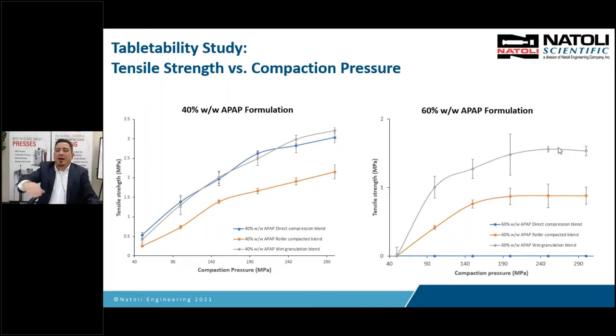This is what I'm talking about with pushing our product until it fails. You see, as we increase pressure, we have this linear portion. Now it's starting to level off. Now it's really leveling off here. Same thing with the dry granulation, a roller compacted blend. You've got this linear portion. Now it's leveling off. This leveling off here is where we reach this maximum compactability or compressibility. We really don't want to compress in that area, because when we're over compressing in this area, this is where we see capping. Capping issues occur when you reach this maximum compactability and you keep increasing that pressure.